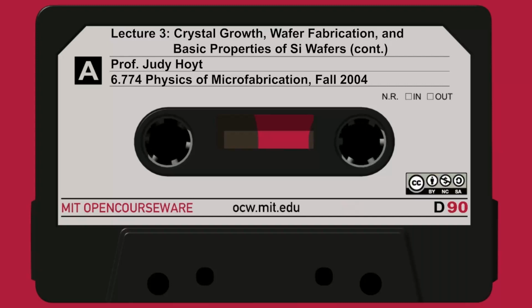Let's go on to slide 4, and we're going to talk about modeling these native point defects. Basically, the presence of native point defects, that is vacancies and interstitials, minimizes the free energy of the crystal. It increases the configurational entropy. If you want a derivation of that, you can look at Mayer and Lau's, one of the textbooks I referred to early in the class. Their 1988 text has a little derivation on that.